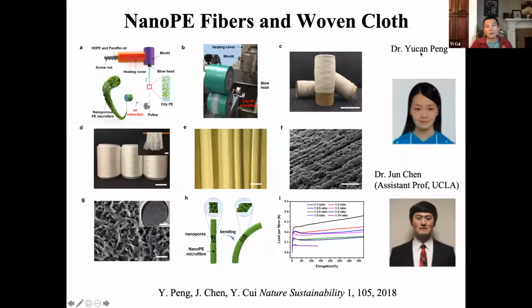And Chan was a graduate student in the group. Jun Chen was a postdoc. Now Jun just joined the UCLA faculty about a year ago. We needed to figure out a way. How do we generate this nanoporous polyethylene in terms of fiber? And then you can weave or knit it into a textile. So we developed a process of mixing oil with polyethylene and heating it up, and then extruding that out in a molten state, right? After you extrude this out, it cools back down, polyethylene becomes solid. And the oil is still maintained as oil, then we extract out the oil.